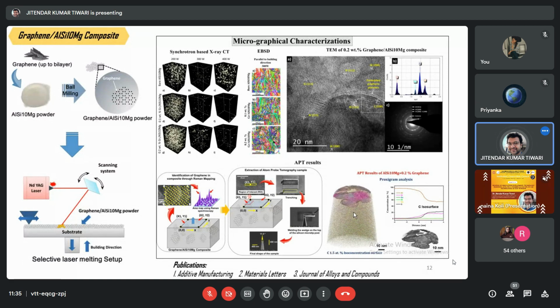If you talk about the melting point of graphene, it is more than 3000, I think, in inert atmosphere. So obviously the temperature does not go up to that level, but there are possibilities that graphene can get damaged, or carbide formation, or its lattice structure may change, and it can be found in the form of simple carbon. So there was a hot rationale in the literature, so that's why I have done atom probe